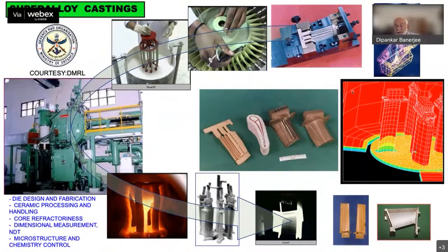And this technology of making single crystals is, to me, one of the most marvelous forms of materials technology. There is, first of all, the design of dies for the casting, for these complex aerofoil shapes, incorporating ceramic cores, which will provide these internal cooling channels in the blade. And then you inject wax into the die to get a shape which resembles the external shape of the blade. And then you dip this whole thing into a ceramic slurry and fire it. And then you remove the wax by steam. And finally, you have a hollow ceramic mold with the core inside that is shown in a cutaway form here. And you pour metal in a furnace into this little hollow over here.